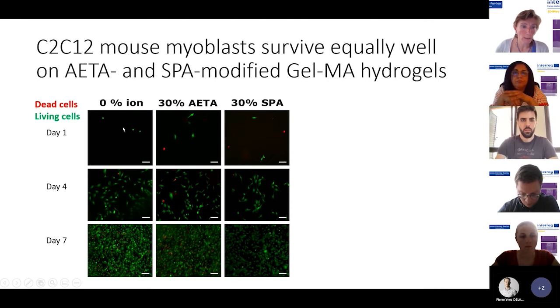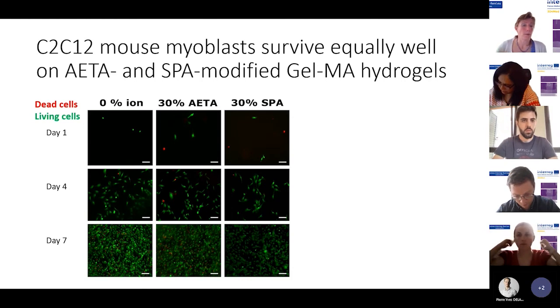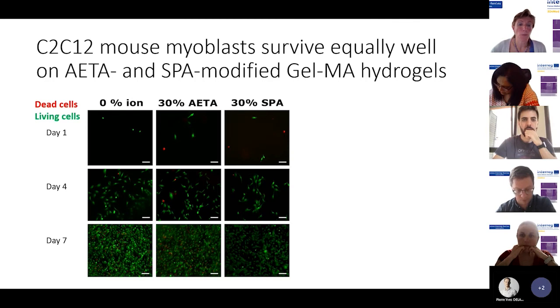So what you see here, the cells are seeded on the hydrogel. And this is day one, so 1 day after seeding. And then the cells are followed up and stained. The dead cells are stained red, and the living cells are stained green. And what you can see is that on increasing days, more and more cells, of course, are there because the cells grow and divide. And then what you can also see is that there are some red cells indeed, but overall, we see that the cells grow well on all hydrogel types, and mostly they are looking healthy. There are always some dead cells in a cell population, but in all conditions, we could see that the cells grew well. So there was no big toxic effect.